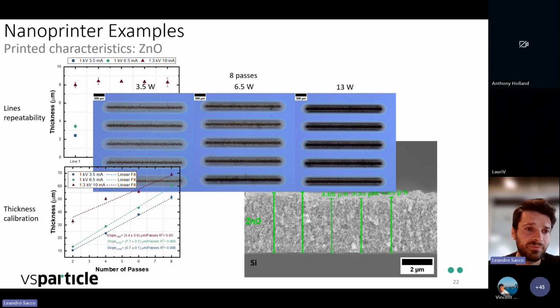And also we did some thickness calibration, because essentially we print in the same position on another substrate, of course, 2 passes, 4 passes, up to 8 passes. So basically we build up a line and we measure the thickness. So with these 2 parameters already, you can get a very good indicator of the reproducibility and how you can calibrate the thickness of the material, the layer that you want to deposit.